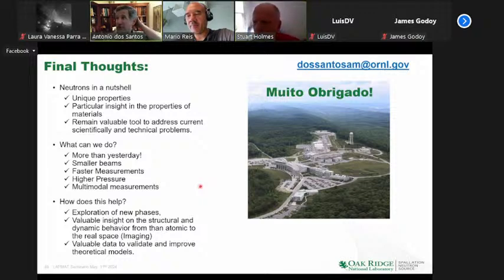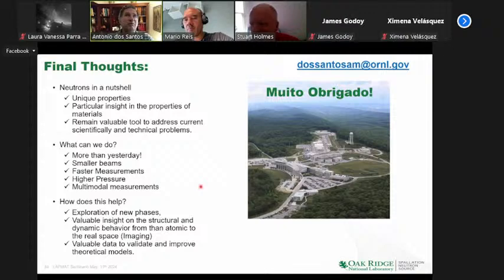Yes and no. So the yes, we have tried some analogs of large hydrides, like yttrium trihydride, lanthanum trihydride, as proxy systems. When there was, I presume I can say this without fear of retribution, the now debunked claim of few kilobar superconductivity, they did try to measure, and we did see Bragg peaks from something that they brought. Now, why is it difficult? It's because many of these phases are called superhydrides, and you go to fairly high pressures, and then you laser heat.